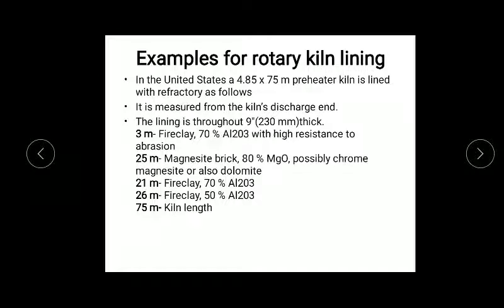for example, in the United States, a 4.85 by 75 m preheater kiln is lined with refractory. Means 4.85 is the diameter and 75 meters is the length of the rotary kiln, and it is lined throughout with 230 mm thickness, that is 23 centimeters. The first 3 meters, that is from the discharge, means at the burning zone.